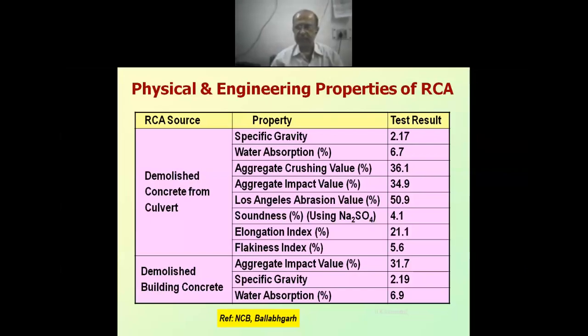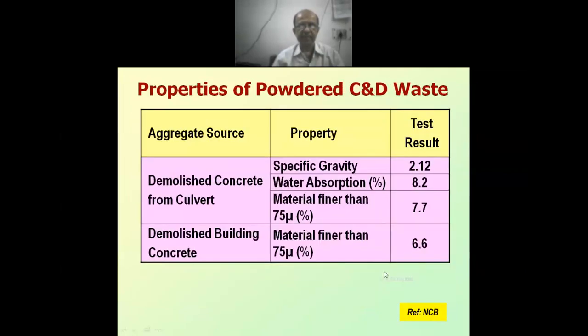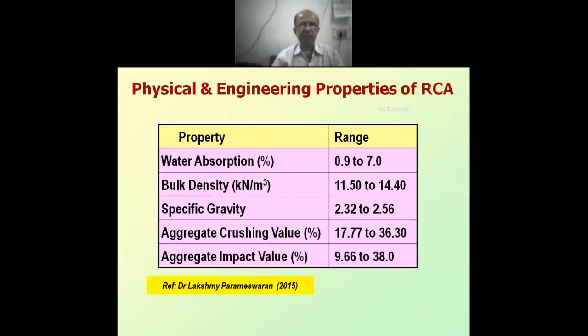Demolished building concrete: aggregate impact value around 32%, specific gravity around 2.19, water absorption around 6.9%. So water absorption will always be more and specific gravity will be less. Properties of powdered C&D waste: specific gravity, water absorption 8%, and material finer than 75 microns is not very high. This is another very important property. Because material finer than 75 micron is not very high, the permeability of this material will be very good. That is why this material can be easily used in GSB.